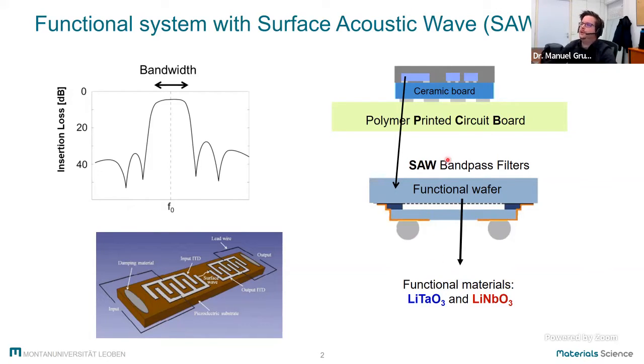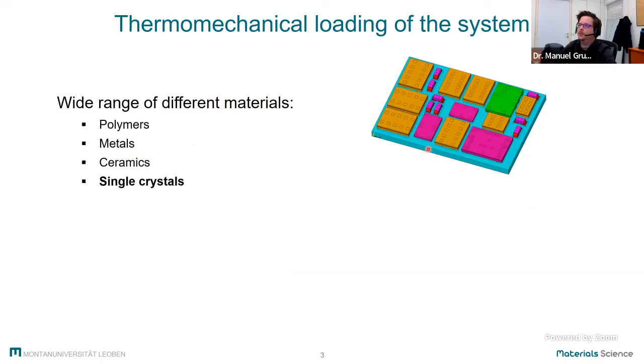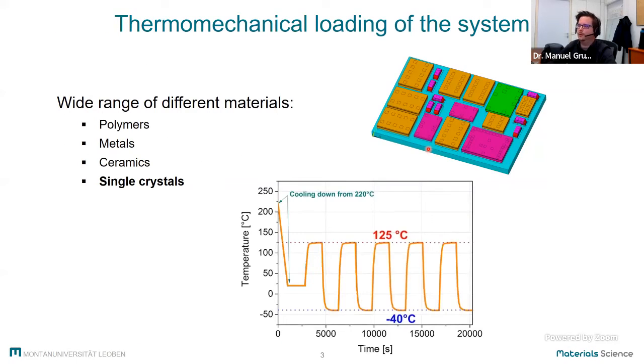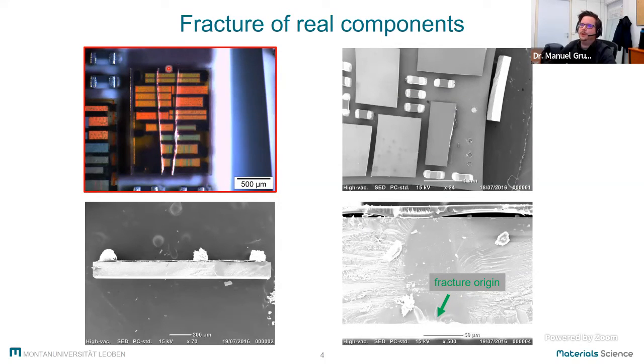So what we can see here is that many different materials are used in microelectronic systems. We have polymers, we have ceramics, we have metallic solder balls, we have the single crystal materials, and all of them have different thermomechanical properties. And this can lead to problems if you think that all the systems are cooled down after manufacturing and they're exposed to thermocycling during qualification and service. So high stresses can occur. And as we see here on a real surface acoustic wave device, cracks can occur. And the functionality of the device can be lost. And maybe the functionality of the whole microelectronic system